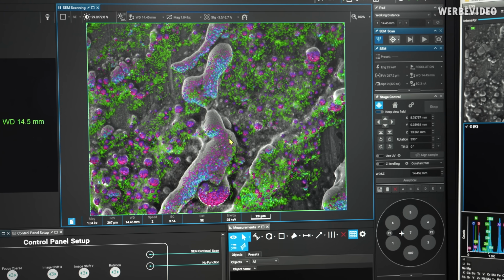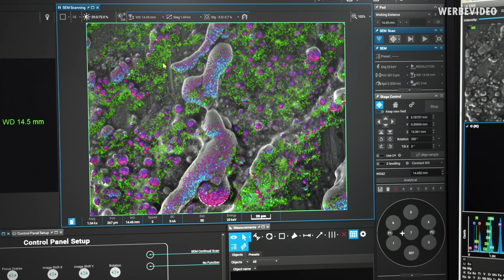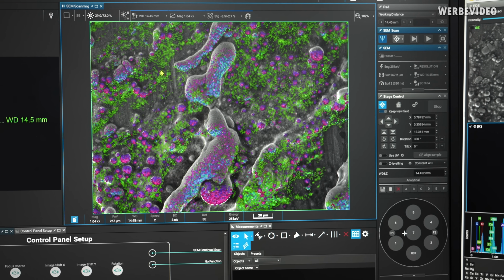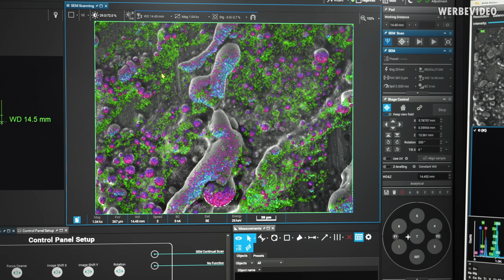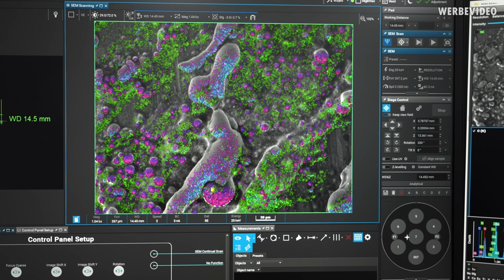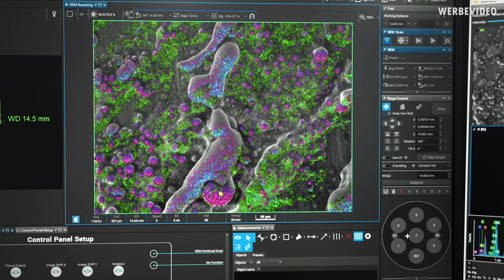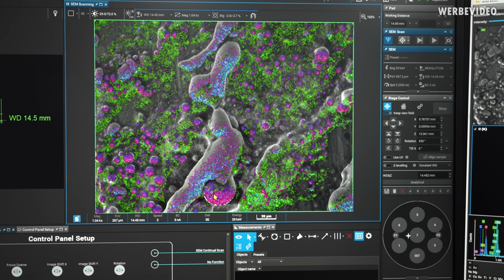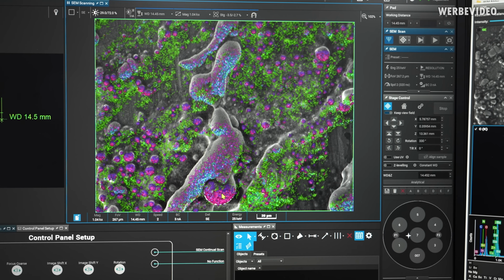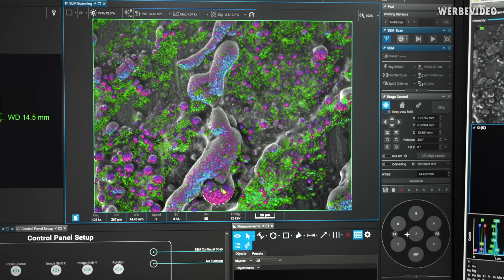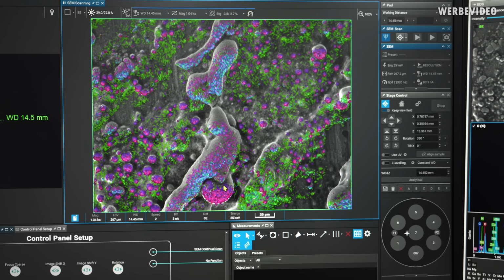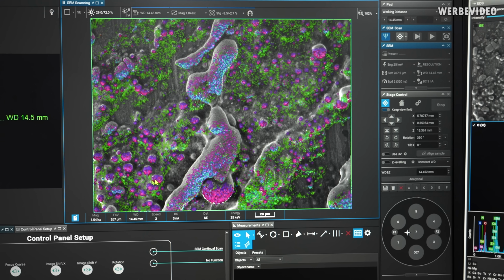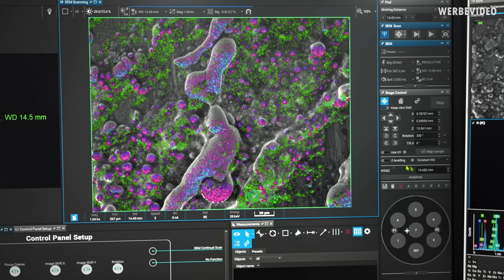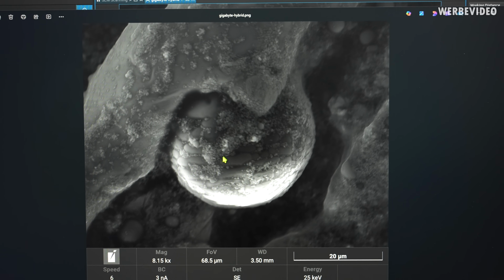Then combined in this image, we can also see a lot of green, which is zinc, but most likely together with oxygen, zinc oxide, very common in thermal interface materials. Then this drop on the bottom is also quite interesting. We can see a lot of aluminium here and also oxygen, so that would make sense that this is probably a drop of aluminium oxide, which is also very commonly used, like also these tiny drops right here in thermal interface materials.